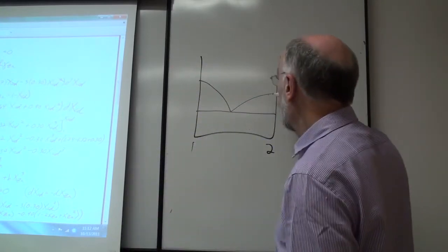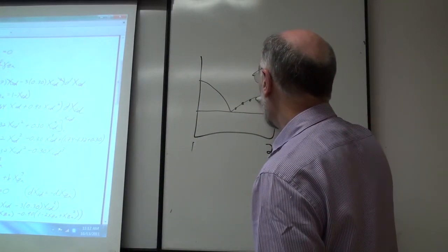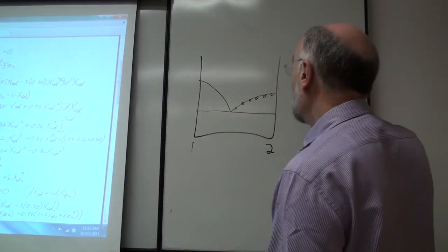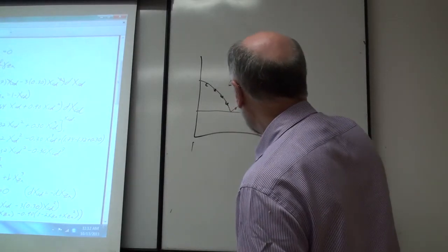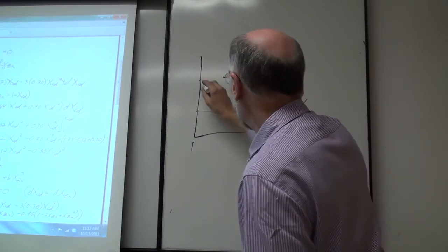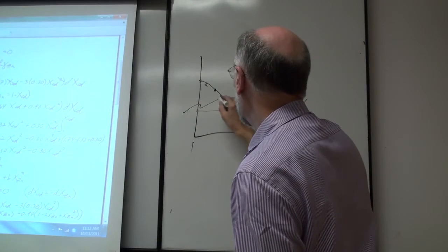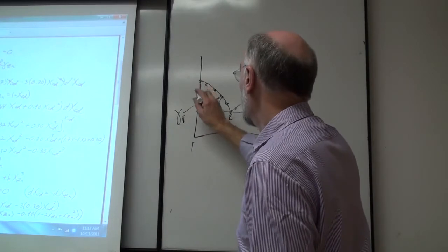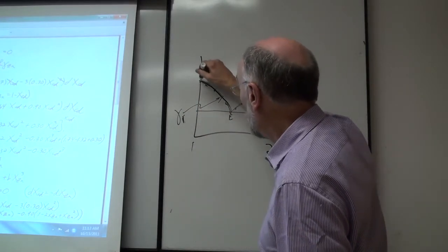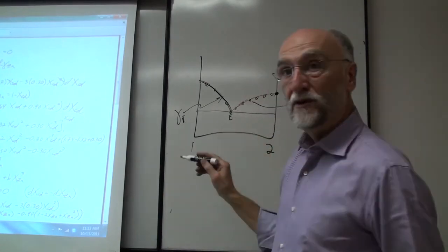Let me show you. Let's say you have a simple phase diagram, 1, 2. And let's say we analyze the system to get log gamma 2 along this liquidus, as we did from the equations. Log activity of 2 is 1 minus heat of fusion, 1 minus whatever. You get the activity. So over this region we have gamma 2, from here to here, and from here to the eutectic temperature we can calculate gamma 1. So gamma 1 is obtained from the phase diagram from pure 1 to the eutectic. Gamma 2 is obtained from the phase diagram from pure 2 to the eutectic.